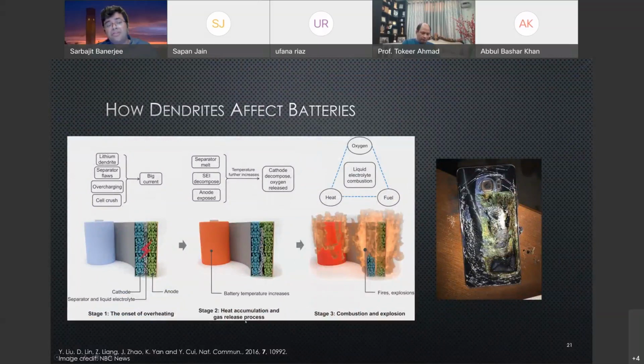Again, what happens with dendrites? If the dendrite actually ends up going across, there's this large current, and then in the case of liquid electrolytes, this is of course incredibly dangerous. As the temperature increases, the flammable components can catch fire. The cathodes will decompose, most of them like lithium cobalt oxide, and release oxygen that will further fuel the fire. And so a combination of oxygen, flammable organic solvents, and heat is a perfect recipe for disaster.